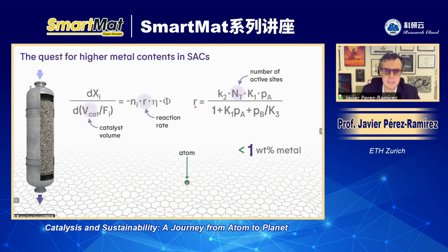If you increase the metal loading, you actually increase the reaction rate. And if you increase the reaction rate, you decrease the volume of catalyst that you need in a reactor in order to achieve a certain conversion. But of course, as I told you before, if you put large amounts of metal, and large means at this point more than 1% of metal, what happens very often is that these metal atoms are not well anchored on the carrier. They will then be mobile, and upon moving, they will form nanoparticles. And then you form clusters of nanoparticles. And therefore, basically, the purpose of the exercise is defeated, because what you want is to increase the density of single atoms. You don't want to make clusters.